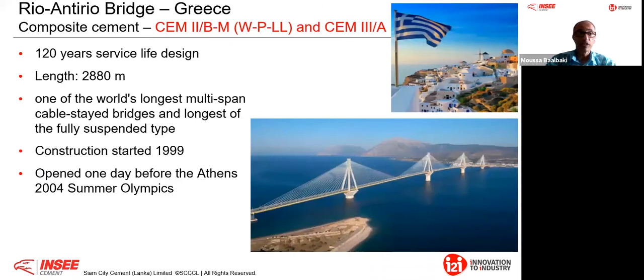The beautiful Rio Antirrio Bridge in Greece. And you see here, it's a CEM2BM, but it is a ternary. Three different additions. M means it's a calcareous fly ash, a natural pozzolan, and a limestone, MPL. Plus, they use CEM3A. This is slag-based up to 65%. You see, this bridge is designed for a 120-year service life. It is not built with the ancestor of this green cement that is OPC.